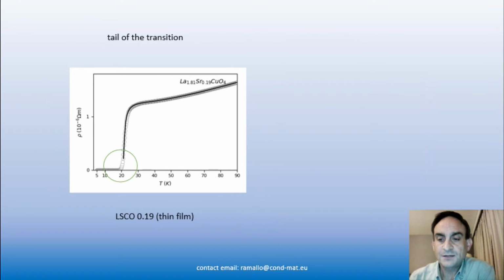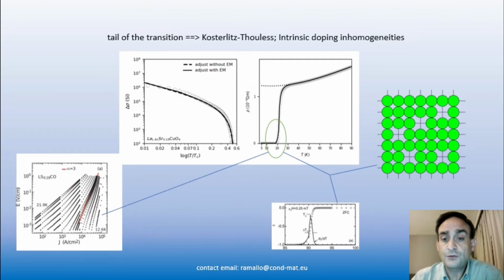So another aspect is the tail of the transition, and for that you have to consider two effects. One effect is the randomness of the distribution of dopants in these materials that naturally leads to a distribution of critical temperatures that fortunately you can measure using the zero-field-cooled magnetic susceptibility that gives you a very direct way of obtaining the distribution of critical temperatures.